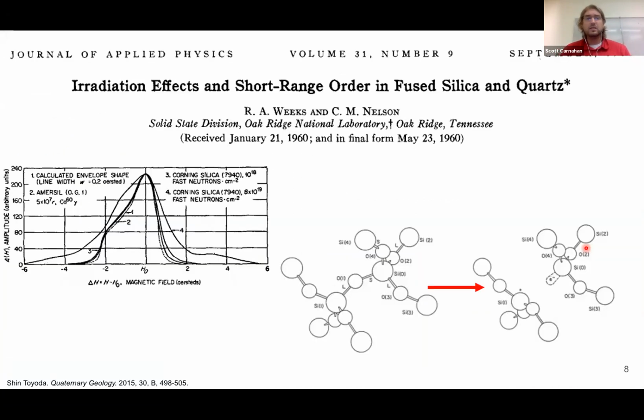I'm going to be talking a lot about quartz because it has some very special features for NMR and EPR. It has some very cool properties. Even as far back as the 1960s, this is one of the most well-studied systems by EPR. Gamma radiation and neutron radiation give the exact same EPR signature for fused quartz. What's happening here is quartz has silicon with a tetrahedron of oxygen around it. During the gamma radiation process, the bridging oxygen is removed, and then there's an electron sitting on a silicon. This is the E prime vacancy, or E prime radical, or an oxygen vacancy.